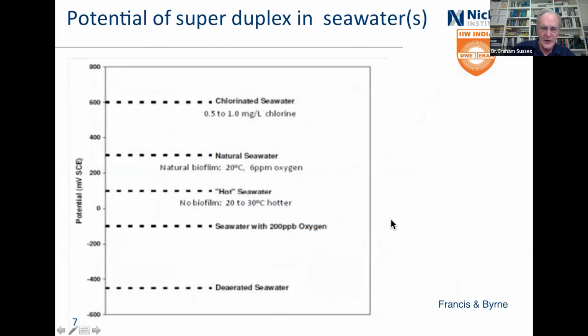There are other things outside, though. This is from Roger Francis's stuff, published by Francis and Byrne. And this is looking at a super duplex stainless steel in seawater. So normal seawater, it sits at about that sort of potential. You've got a biofilm on the surface. You've got a bit of oxygen there. If you heat the thing up, so it's 20 or 30 or so degrees more, then no biofilm, no potentiation of the oxygen, and so it drops to there. You can deliberately deaerate it, pull it down to there, or if you completely deaerate it, down to that point there. If you want to go the other way, then chlorinate it.